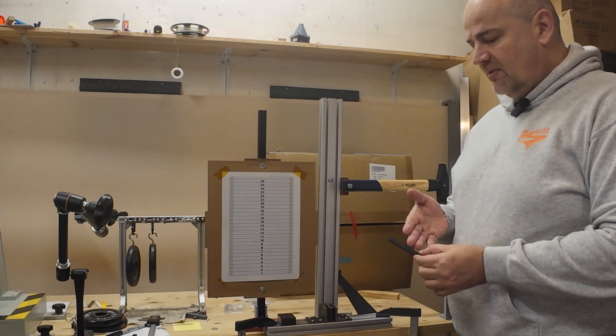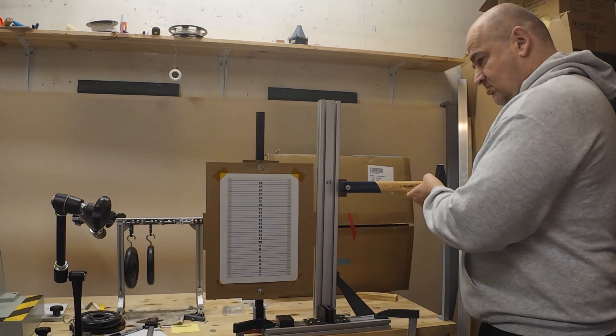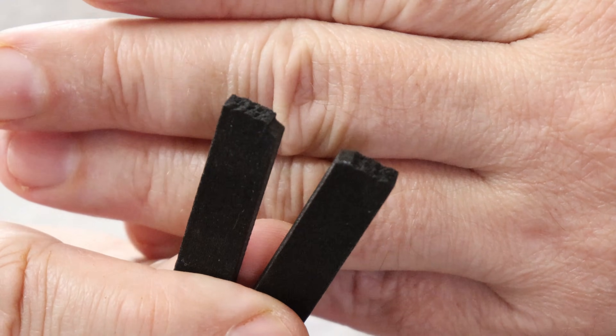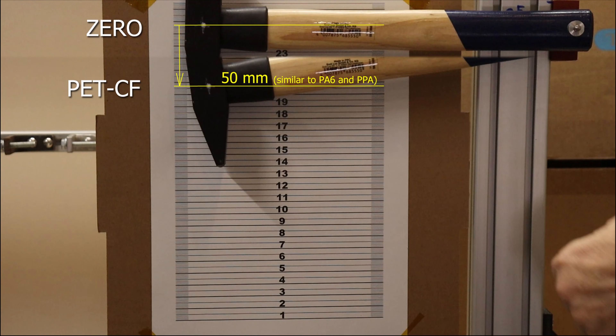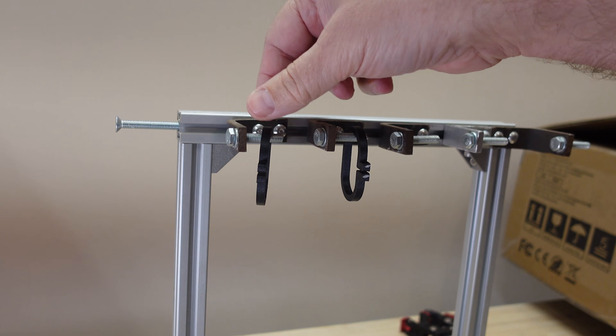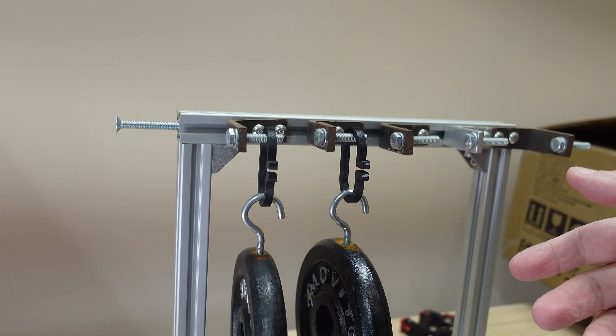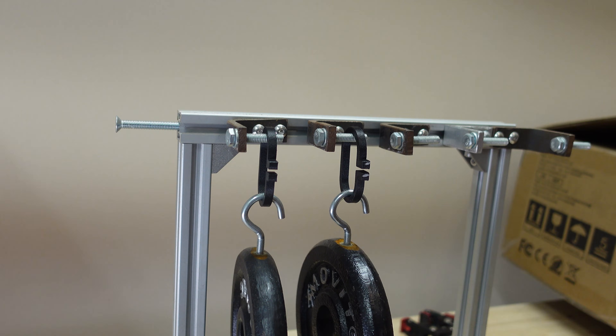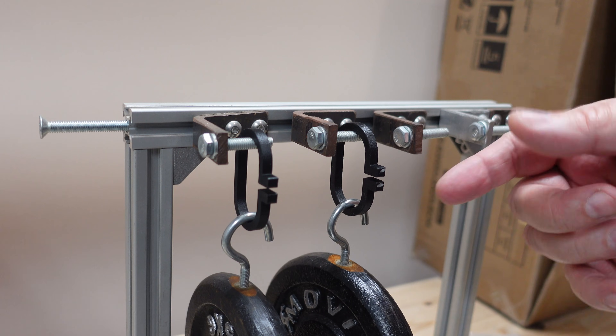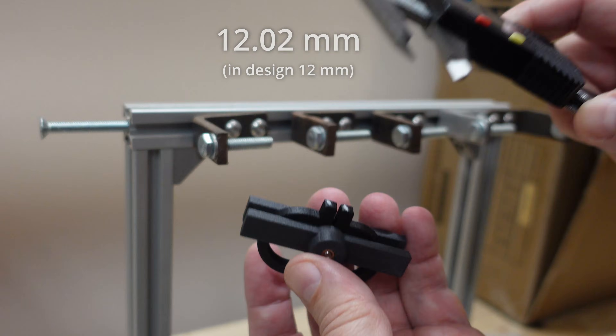Impact test — I'm not sure what to expect. The filament CF is brittle but I'm unsure about the printed object. It looks like it is tougher compared to BambuLab PA6 filaments, and the toughness is actually very similar to PA6 or PPA-CF materials. Creep test: deformation under a constant load of 1.25 kg run in parallel for PPA-CF nylon and PET-CF. I already measured — slightly more deformation on the PET compared to PPA. Both materials perform well, and the additional deformation of the PET-CF compared to day zero is only 0.2 mm. Even the measurable permanent deformation is very minimal on this test object.